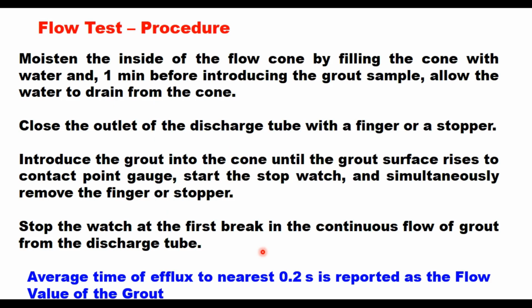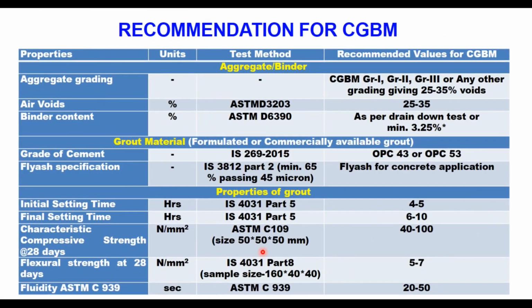For satisfactory performance of CGBM in the field, IRC SP 125 has given some recommendations for the design of this mix. The grading can be either grading 1, 2 or 3 depending upon the requirement, or you can also design your own grading giving 25 to 35% air voids. The binder content is as per the drain down test, but minimum 3.25%. The grade of cement for grout can be either OPC 43 or 53, and if you are using fly ash, it should be tested as per the IS code.